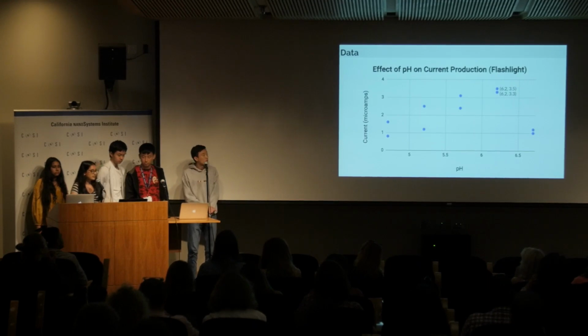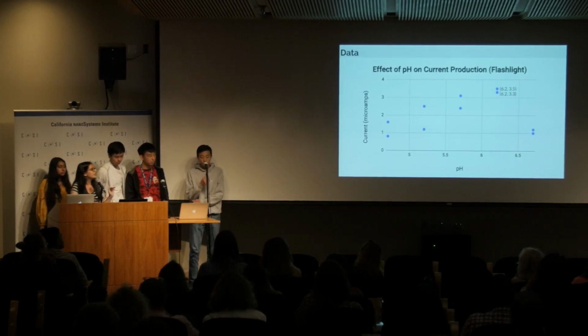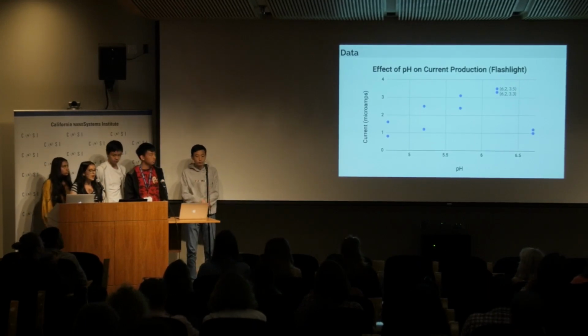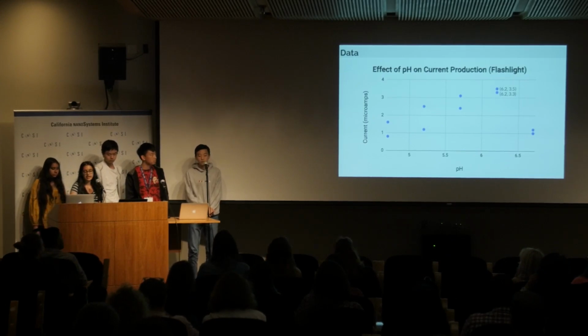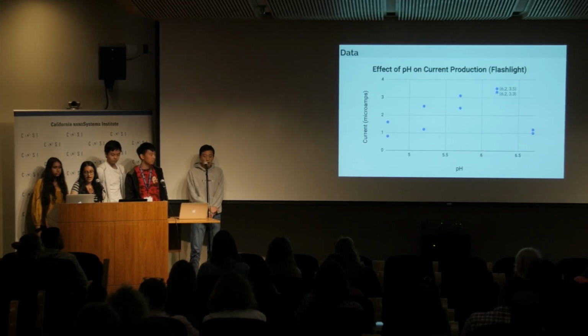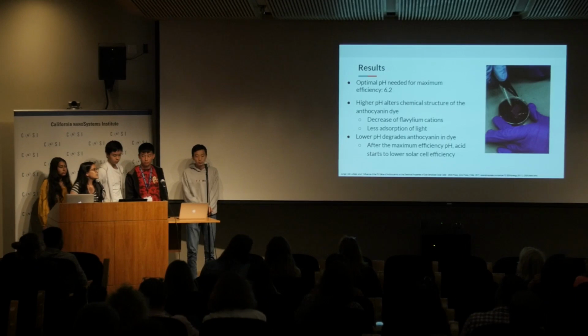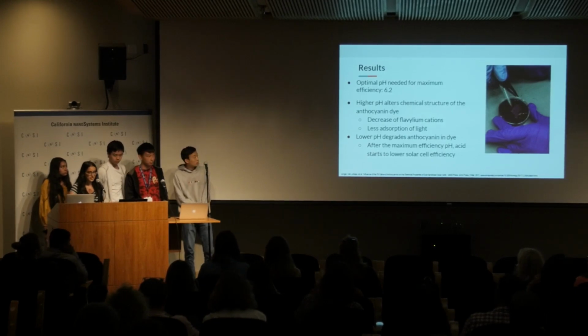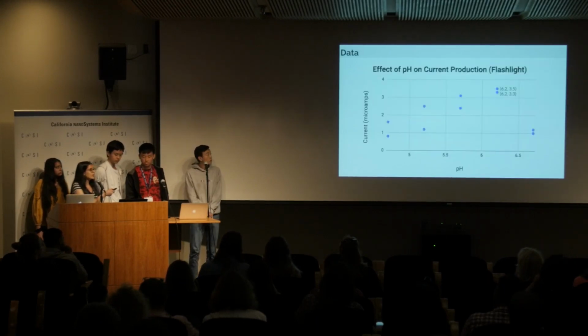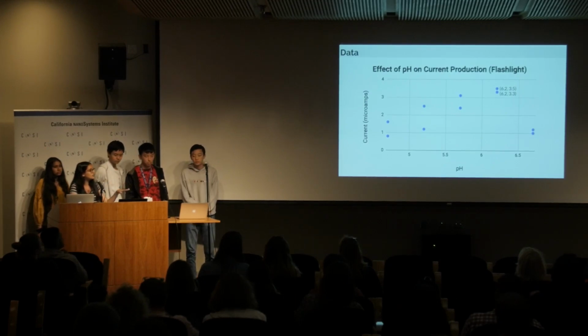And on this graph, this tested the flashlight, and you can see here again 6.2 is the optimal pH, and it gave a current of 4.1 microamps and 3.2 microamps. And so what we concluded was the optimal pH was indeed 6.2 for the best efficiency. And you can also see in the graphs that at too acidic levels, the current produced is super low, and at too high of a pH, the current produced is also low.